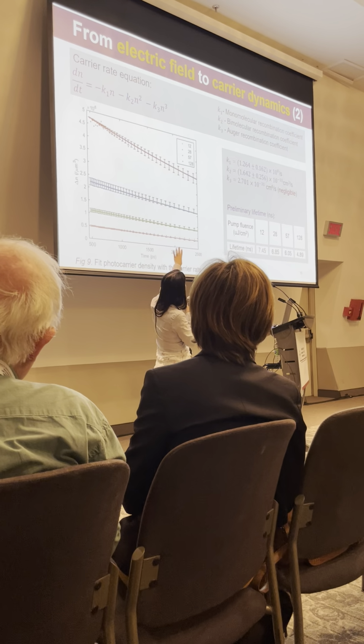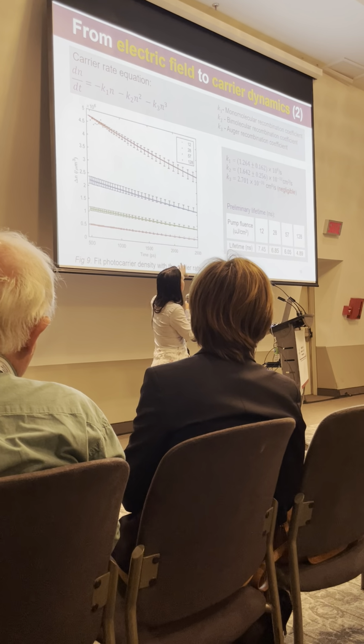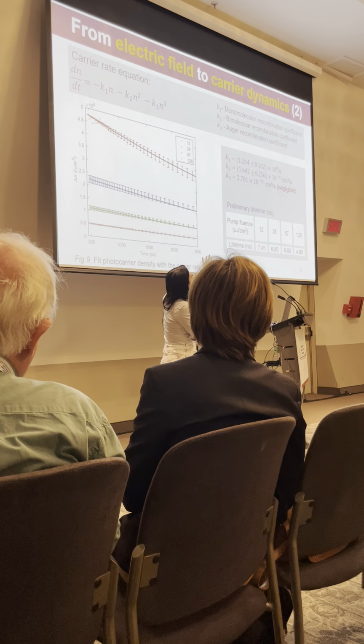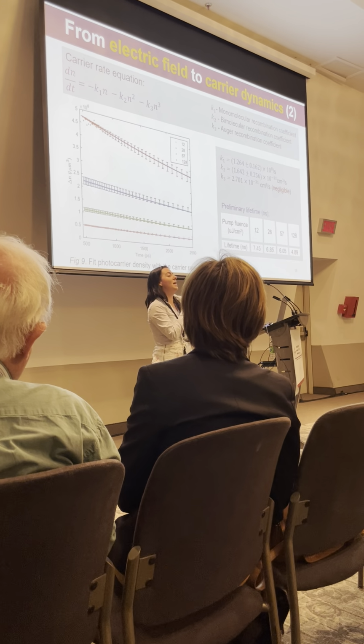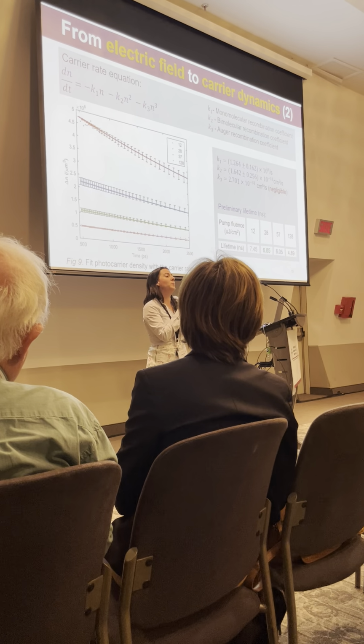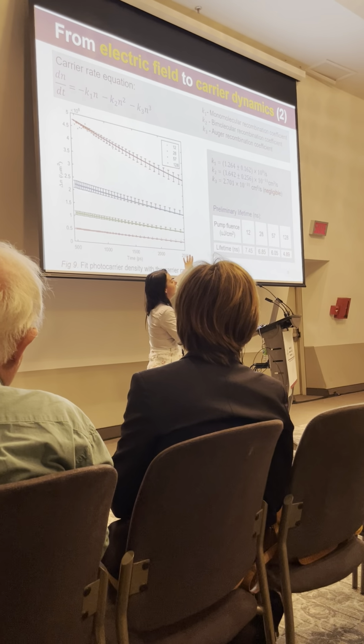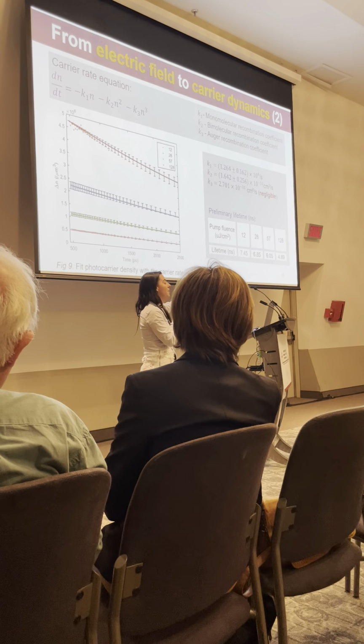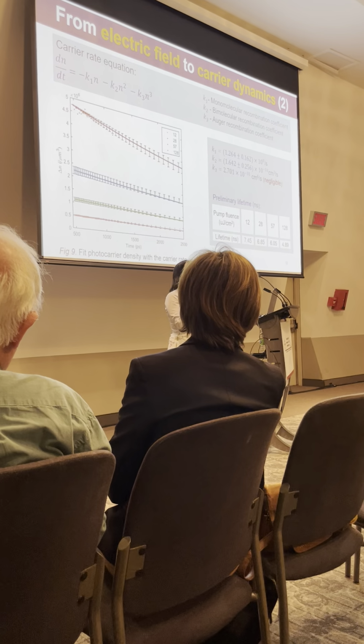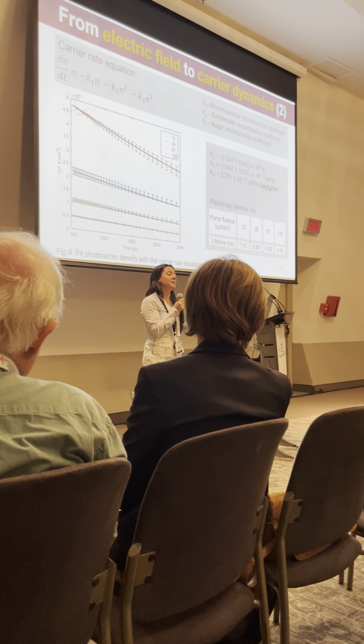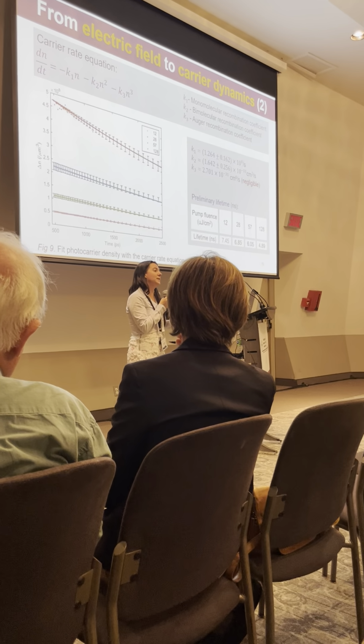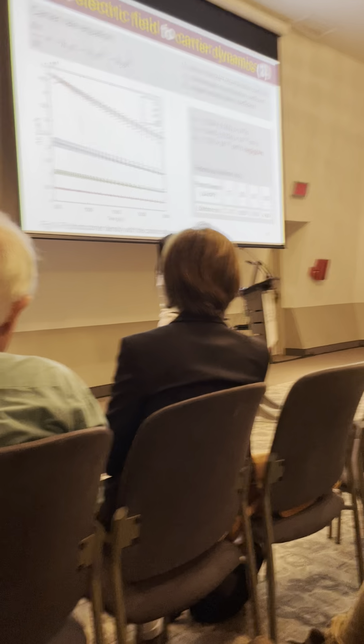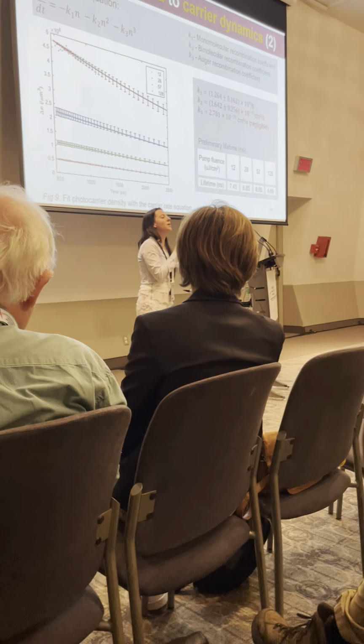And this is our fitting here that we've done on this data, and our bimolecular recombination constant that we've extracted matched literature for this zinc phosphide, so we're pretty confident in that, but we do have quite a large monomolecular term there. So that was actually really informative for our collaborators to go back and look at their growth process and see why we might have these defect states or trapping that could be contributing to that.